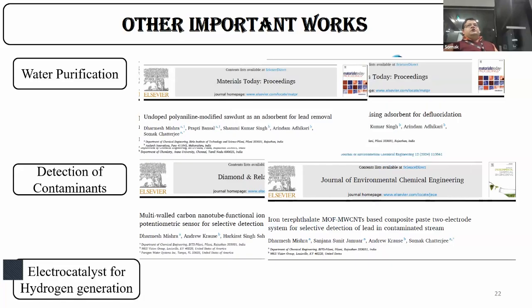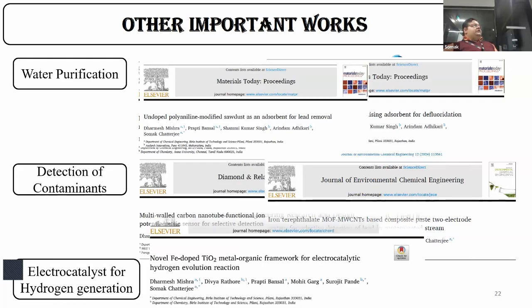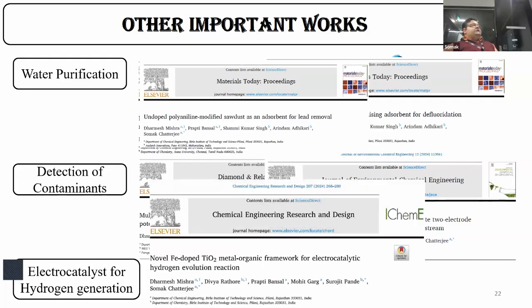We are also working on electrocatalysts used for hydrogen generation from wastewater streams. This is a new area that I started in collaboration with one of my senior colleagues at Pilani. We used a metal organic framework, a titanium-based MOF, with different types of doping. In this case, we used a novel iron doping, used for the first time for electrocatalytic hydrogen evolution reaction.